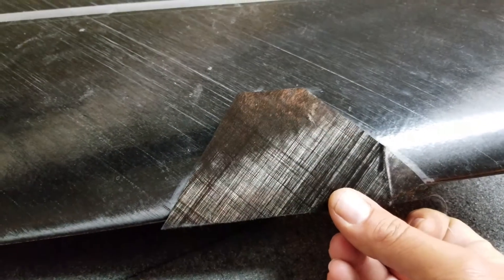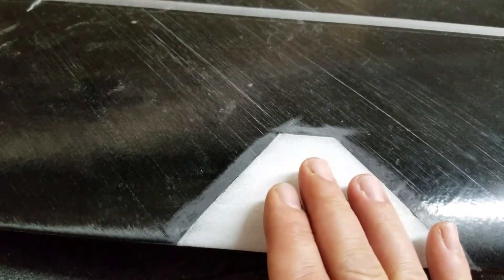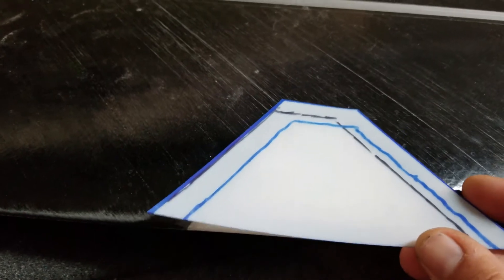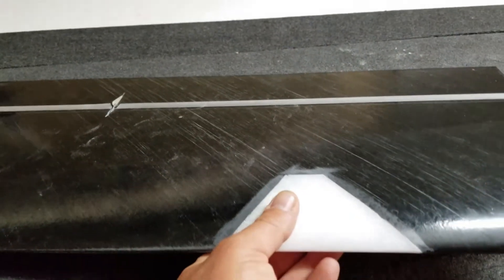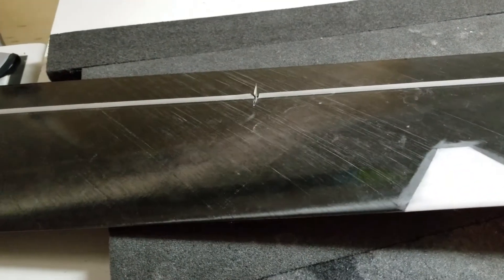For the bigger damage where the chunk of foam was, I'm going to use some spread toe carbon — you could use other carbon or fiberglass or whatever you have. I'll put the carbon on, wet it out, soak up excess resin, then tape pieces of mylar to the wing and put the whole center panel in the bag to get good adhesion and compression on these areas.